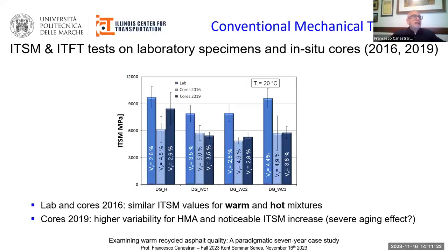When comparing the indirect tensile stiffness modulus of laboratory specimens and cores taken in 2016, looking at the first and second set of bars of the histogram, we can see that warm and hot mixtures show similar values. Whereas, when considering cores taken in 2019, we observe higher variability for hot mix asphalt specimens and remarkable stiffness modulus increase, likely due to more severe aging effect in the case of hot mixtures compared to the warm mixtures.